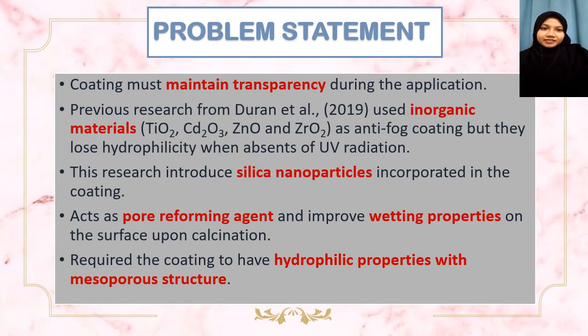From previous studies, the coating is made from inorganic materials such as titanium oxide, cadmium oxide, zinc oxide, and zirconium oxide. However, these materials tend to lose their hydrophilicity in the absence of UV radiation. Due to that problem, this research introduces silica nanoparticles incorporated in the coating to act as a pore-forming agent and improve the wetting properties on the glass surface upon calcination. The coating will have hydrophilic properties with a mesoporous structure. Thus, it allows the water droplets to form a continuous thin film with minimum light scattering.